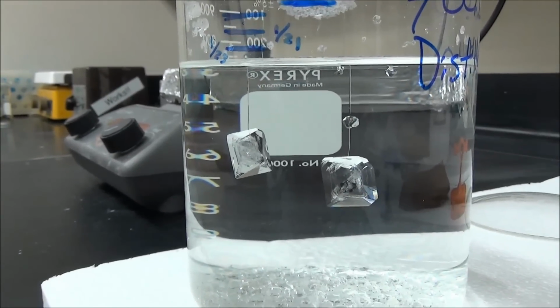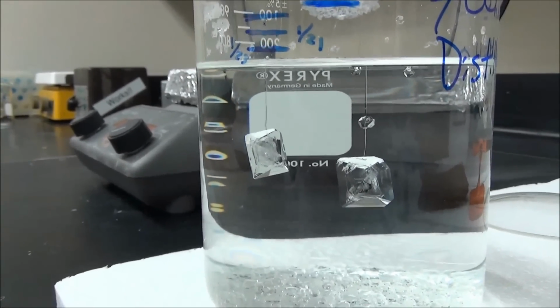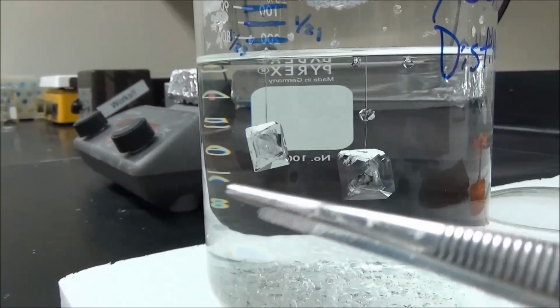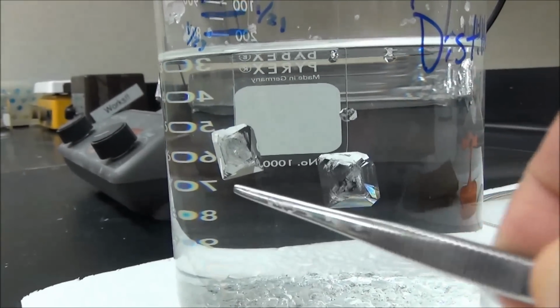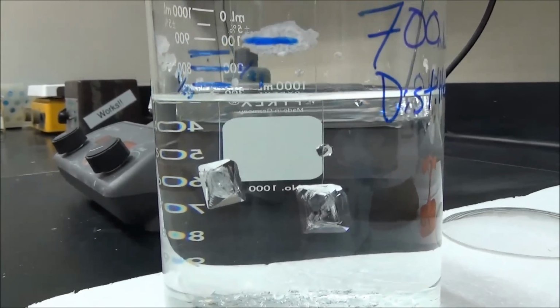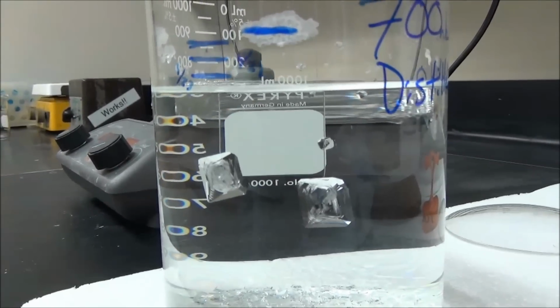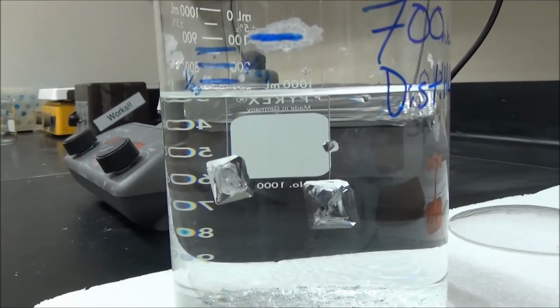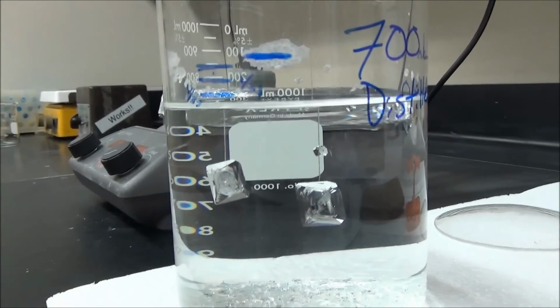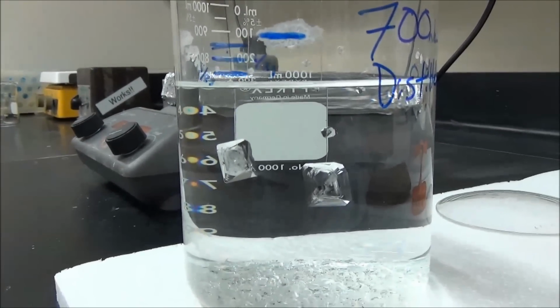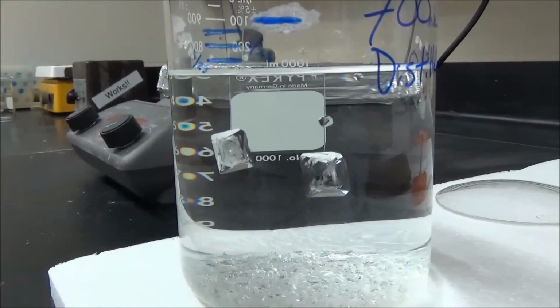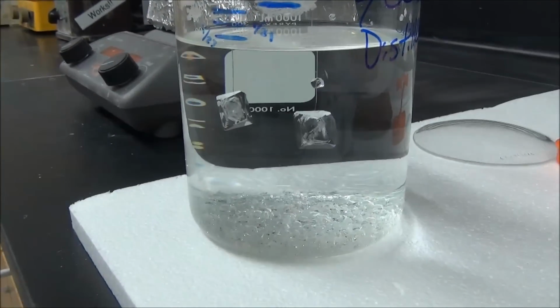But basically, the fact that we see a little bit of these inclusions in the crystal, that banding, if we try to grow the crystal much faster than that, we'd see a lot more of that banding and our crystals wouldn't look so good. So in fact, our crystals are actually growing at a pretty good rate right now. Any faster and they probably wouldn't look quite as pretty.